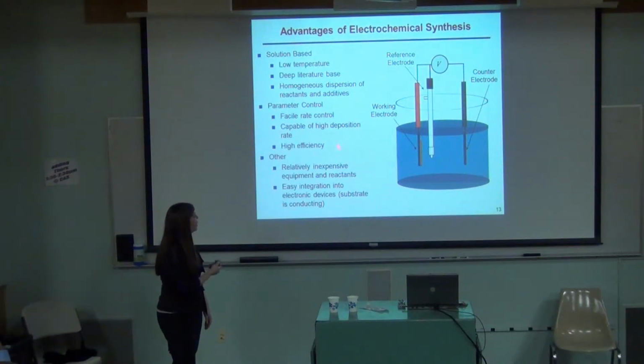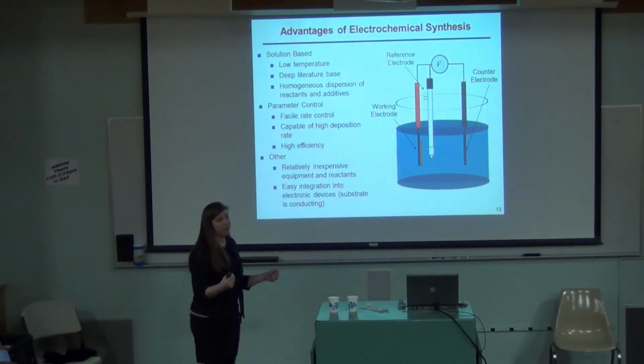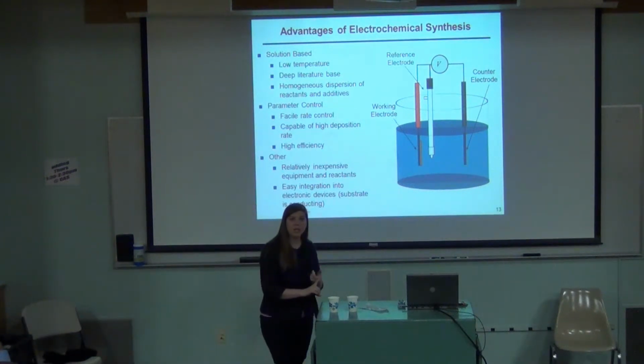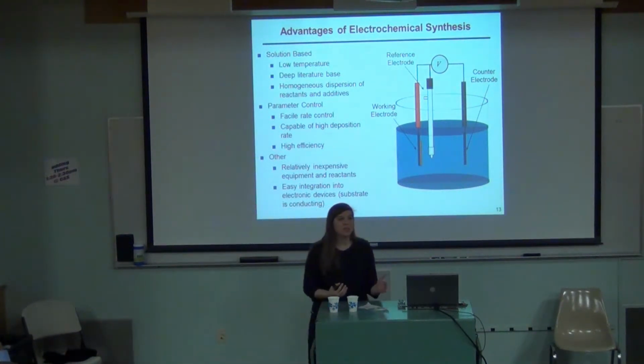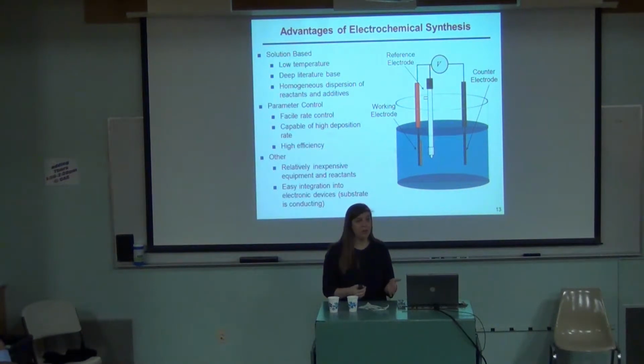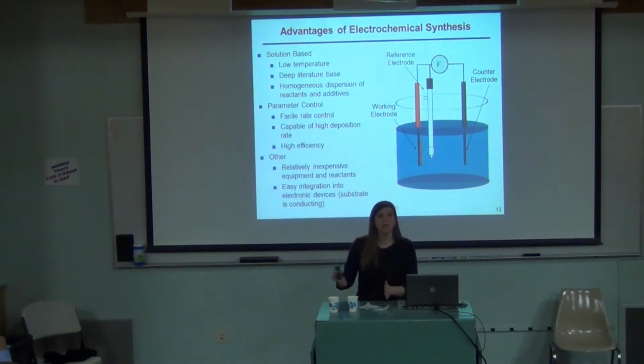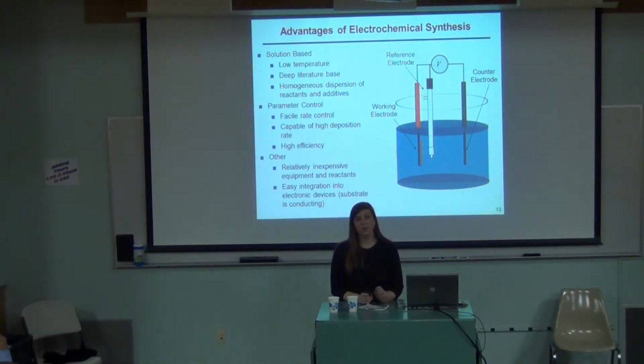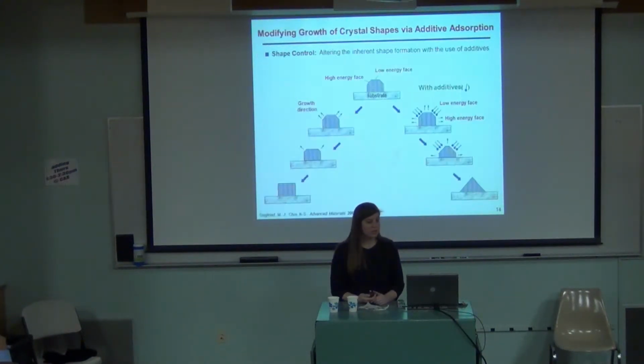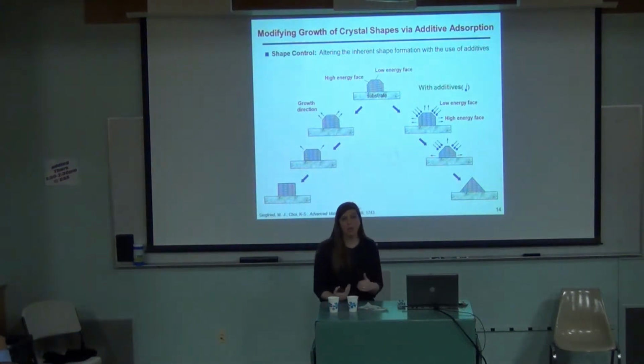The other thing is it's very easy to make, and it's relatively inexpensive. It just involves a 3-electrode setup. You just need a working electrode, which is where the process of oxidation or reduction is happening. Whether you want it to be oxidation or reduction, that will depend on your system. And then the counter electrode is just where the opposite process happens. And then the reference electrode is just there to help you keep those potentials consistent. So that's how I make all the materials, and the people in my lab make all their materials.